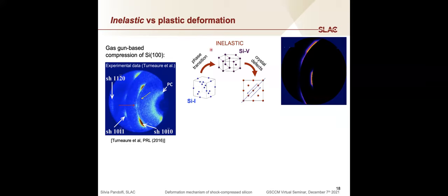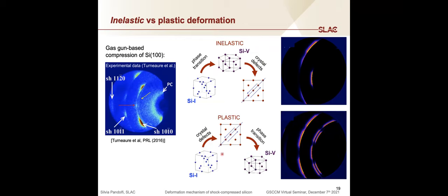hypothesize an inelastic deformation for which the phase transition is the main shear release mechanism, and then it's just temporarily followed by the development, generation and motion of defects, so of plasticity, the strongly preferred orientation should be visible also in this experimental configuration. However, if we perform the same calculations,